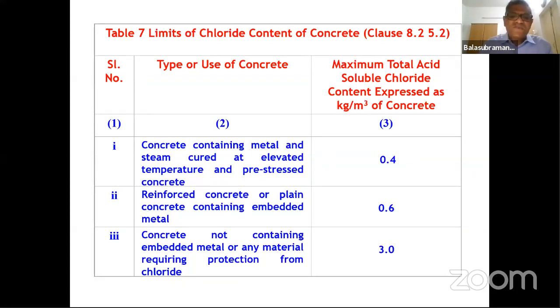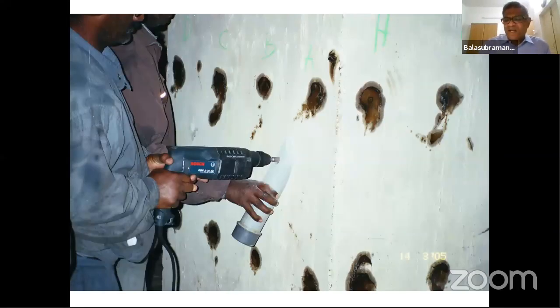The chloride should not be greater than 0.6 kg per meter cube. But at most of the sites we go to, it is around 1, 2, 3, sometimes even 4 kg per meter cube in marine structures. And the best way to do a powder sample test, actually my colleague Dr. Manu does it, and I find in European countries like Norway, they do this. They take a core, put it in a lathe and in a chuck, and then use a tool and cut the powder sample. So that is more precise.